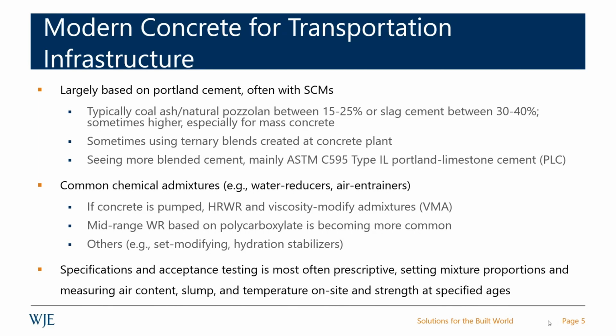Admixture wise, for most of our structures we use quite a bit of high range water reducing admixtures, and viscosity modifying admixtures for pumpable concrete, flowable concrete. We're seeing mid range water reducers that could still be based on polycarboxylates for paving. And then you can use set modifying and hydration stabilization for some applications. So a lot more chemistry is happening within our concrete than in the past. Specifications and acceptance testing most often remain prescriptive. We're looking at basically air content, slump, temperature when the concrete's delivered, and then we break cylinders typically for acceptance, sometimes beams. So not much has advanced on the testing front overall.